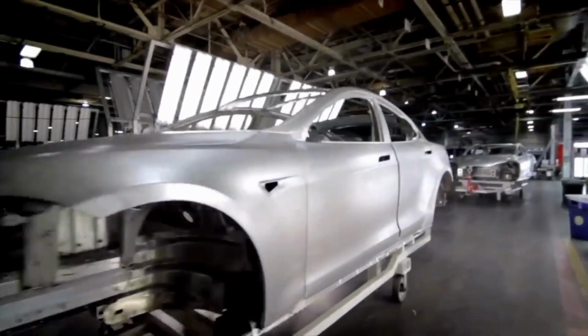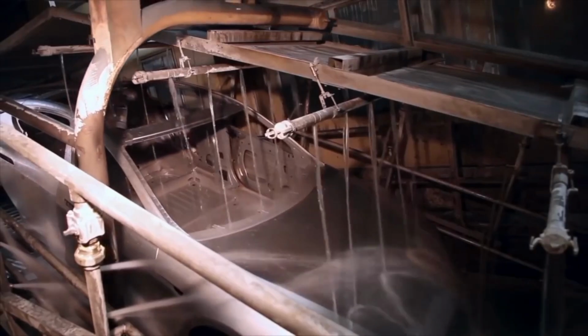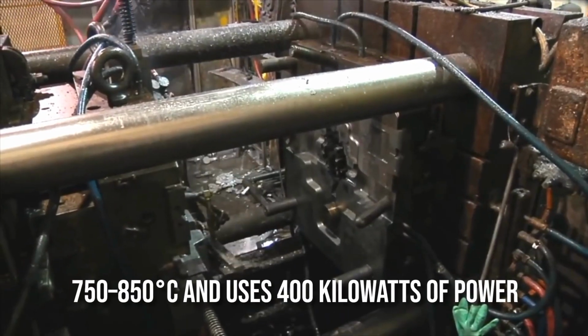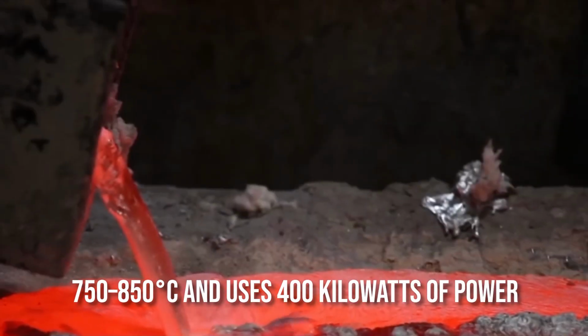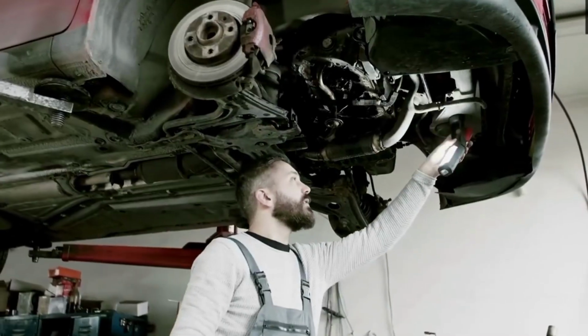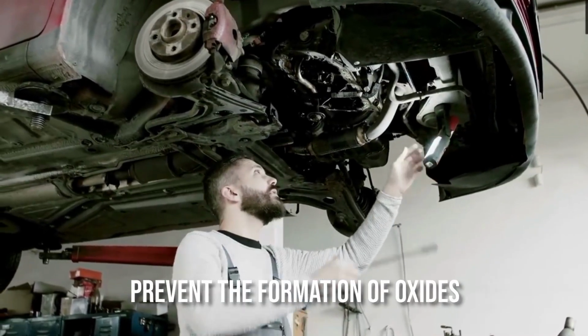The remaining liquid metal is pumped into an enclosed warming oven that operates at 750 to 850 degrees Celsius and uses 400 kilowatts of power. A tank blanket of nitrogen gas is placed over the molten aluminum, which is circulated to maintain an even temperature and prevent the formation of oxides.